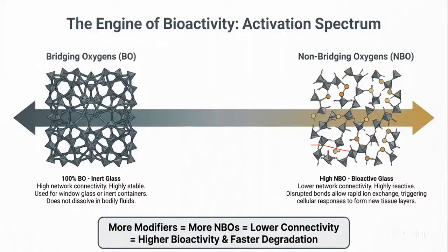Now, before getting into the optical property, one of the major things that I would like to tell you is that glasses are also found to be effective, particularly in the bioactive region. How bridging oxygens and non-bridging oxygens help in bioactivity is what I'm going to tell here. If the bridging oxygen is 100%, which means high network connectivity, they are highly stable. When the network connectivity is very high, they will not try to dissolve or interact with any bodily fluids that we are trying to use.